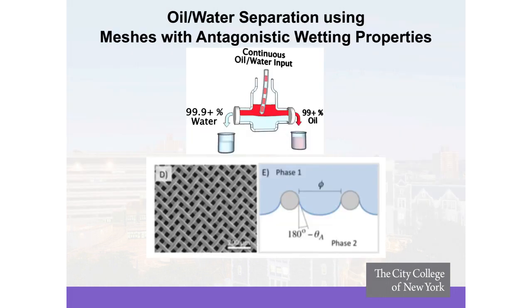Another approach where we can utilize wetting phenomena or selective interfacial interactions between a liquid or two liquids and a solid substrate is for the separation of oil and water using meshes that have antagonistic wetting properties. So, for example, if we have a mesh that is wettable by, let's say, a water phase, but not wettable by an oil phase, then by utilizing this approach only the water droplets are going to be able to move through the mesh pore while the oil droplets will be captured, and one is able to phase separate water from oil quite efficiently.